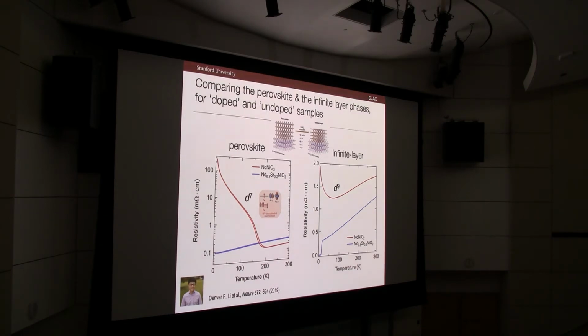So if you take these starting materials and pull out one of the planes of oxygen to get to now O2 phases, if we look at the undoped parent compound, we see something a little bit strange. It's not really a good metal or an insulator. We have a weak, roughly logarithmic upturn. But for the case that we've now chemically hole doped this, nominally at the 20% level, indeed this thing looks superconducting. Right? In fact, if I don't label this, this doesn't look so far even in the resistivity scale from a cuprate.